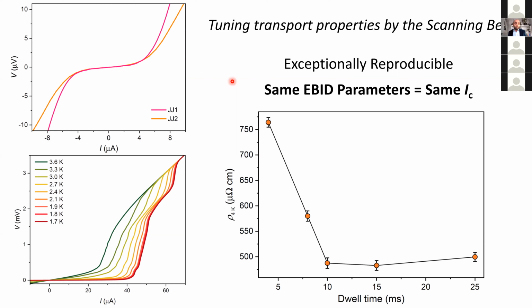But what I think is happening is that there are two different approaches to getting reproducibility. One approach, of course, is to go to a very, very pure, ultra clean system where you get rid of all impurities and defects and you control your system that way. But the other approach is to use a material that is by its very nature already very disordered. It's in fact so contaminated that it's not even sensitive to day-to-day variations in the impurity levels. That is the only way I can explain why these devices are so reproducible.